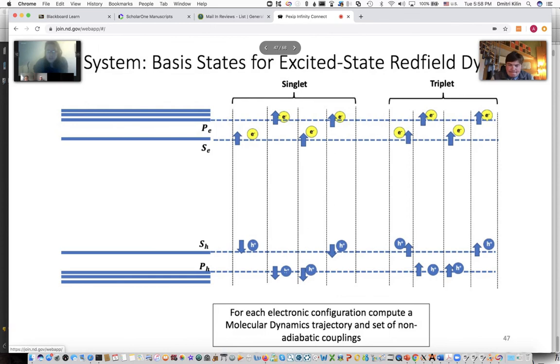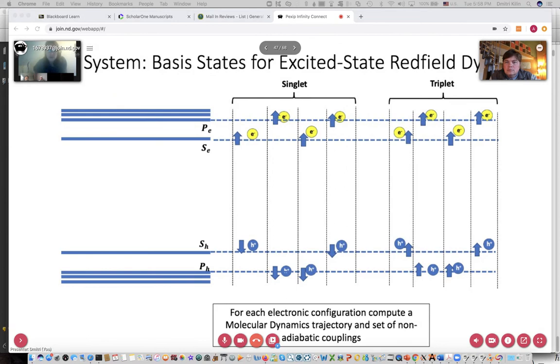And so the previous figure was just an example of one configuration. But what we want to do is model the PE to SE or PH to SH relaxations. So we compute various electronic configurations reflecting these occupations, and we screen for singlet configurations and then triplet configurations. So we just do our homework and look at different spin possibilities that can happen during the dynamics. And then for each of these configurations, we run a molecular dynamics trajectory and compute a set of observables. But mainly what we want is non-adiabatic coupling.